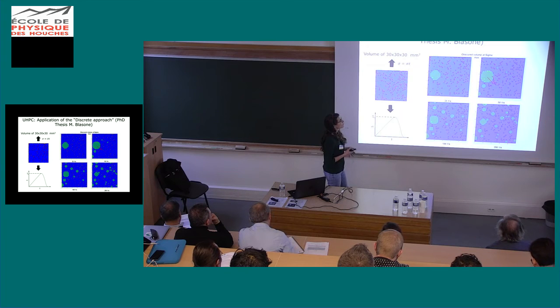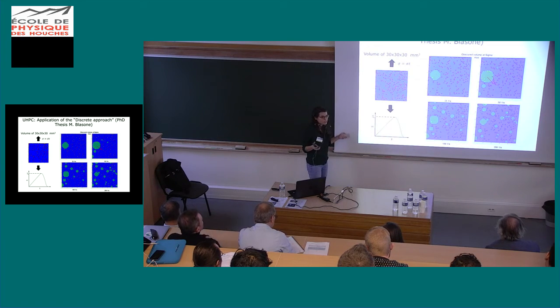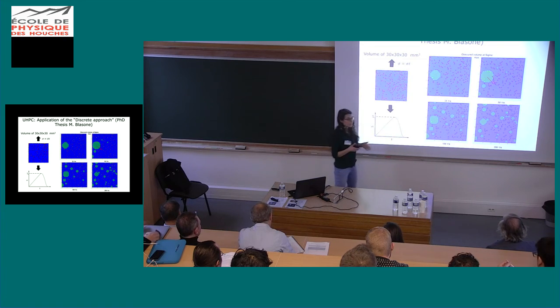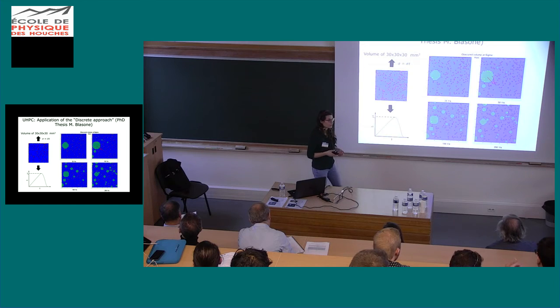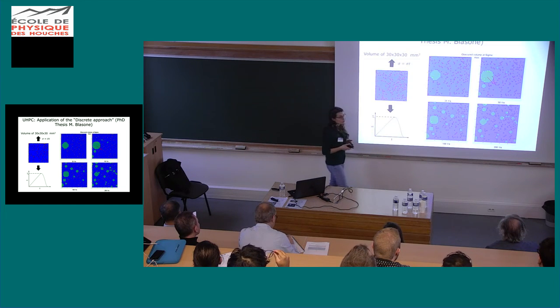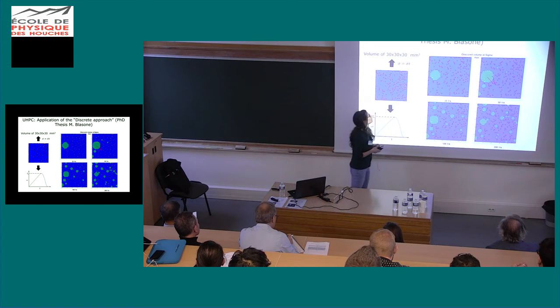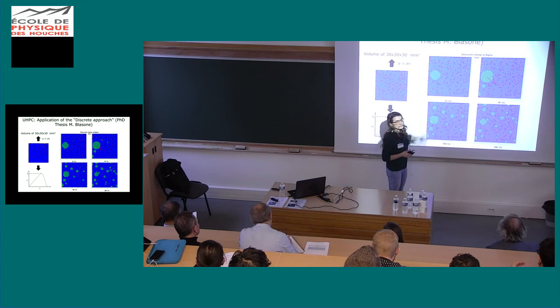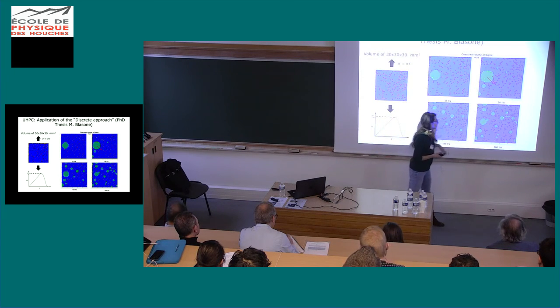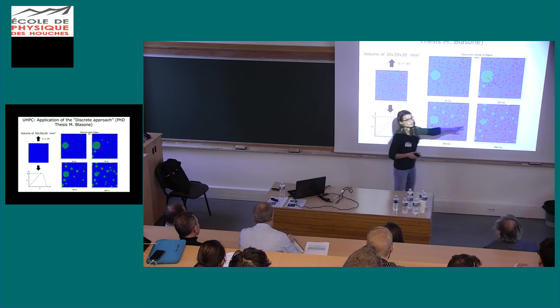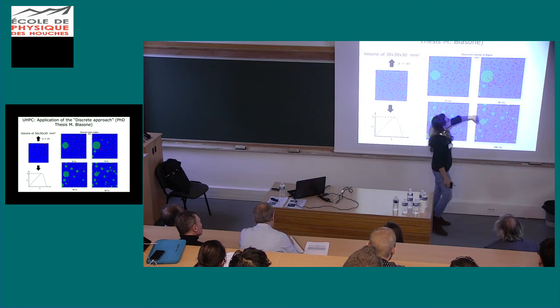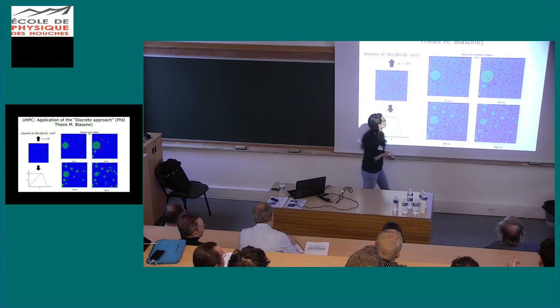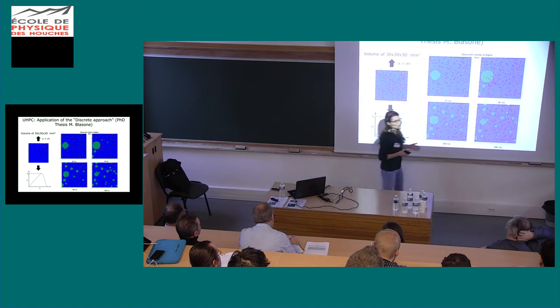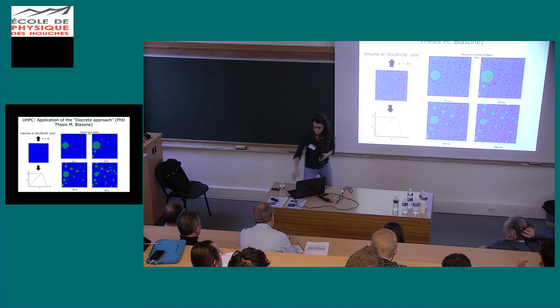What we observe here, just with this simple discrete model, is that for different strain rates we have a different fragmentation. Here I plot for one section the obscuration volume at the peak strength. So we can see that for low strain rate, just one pore initiates. As the strain rate increases, the number of pores that initiate is getting bigger and bigger. And the velocity of propagation of this obscuration zone is constant. It is assumed to be proportional to the wave speed.